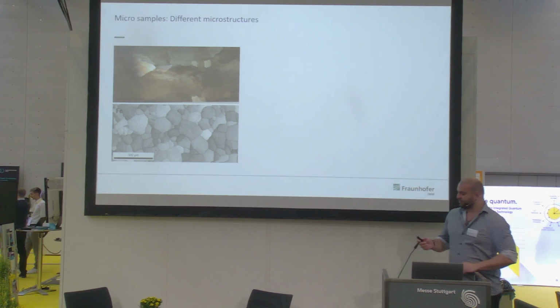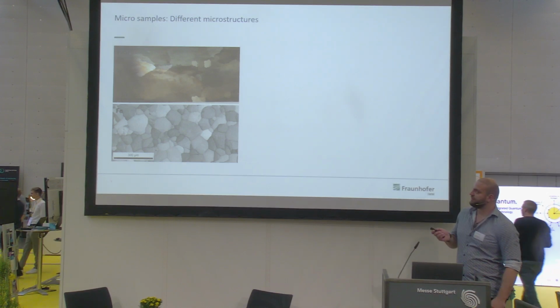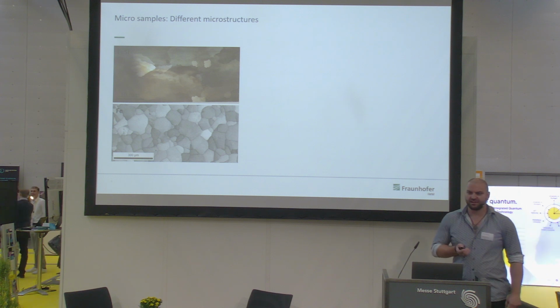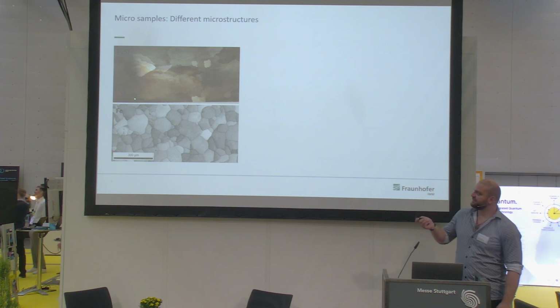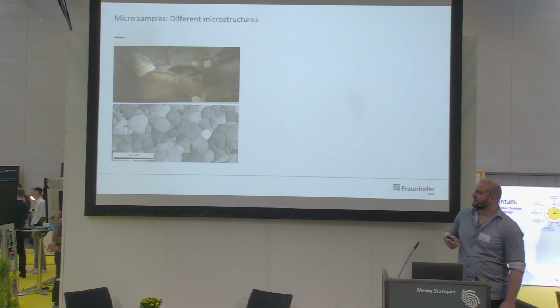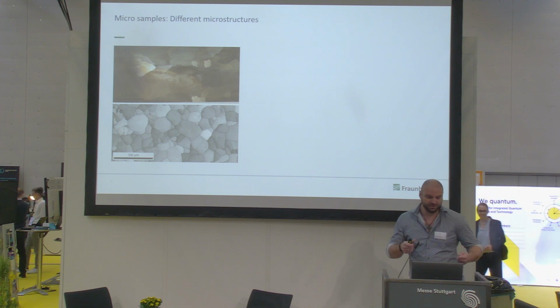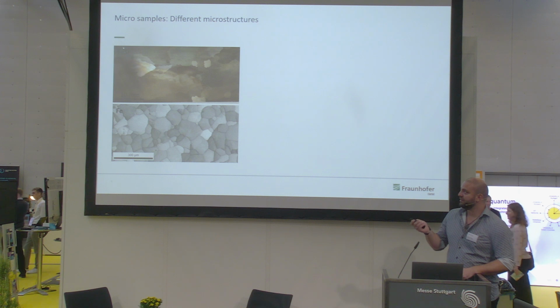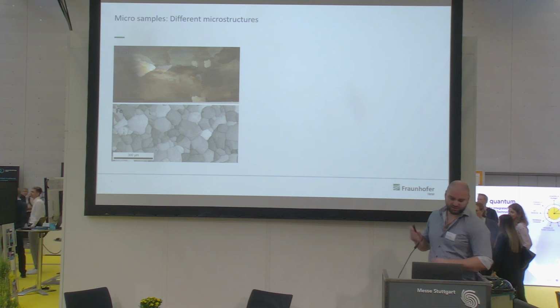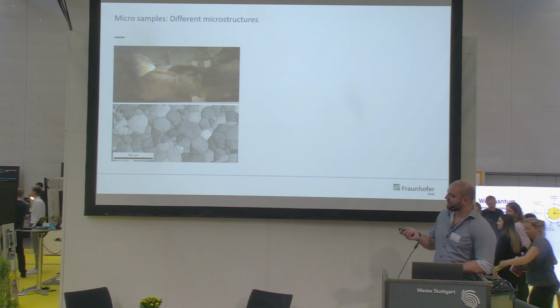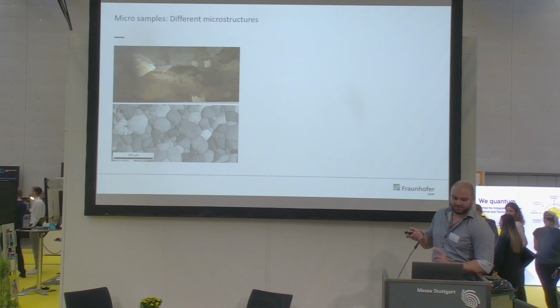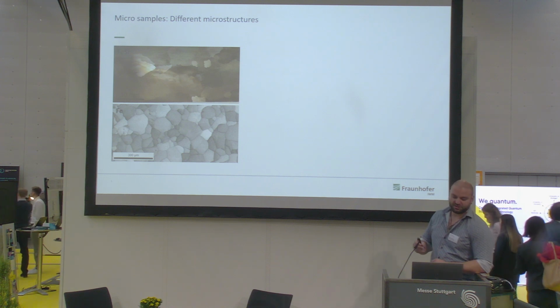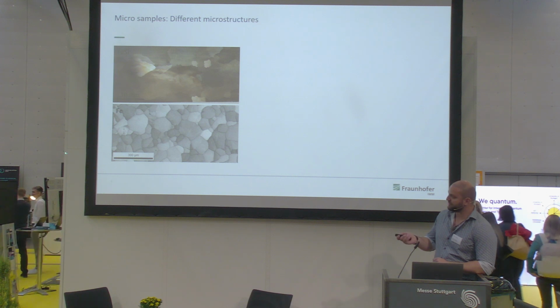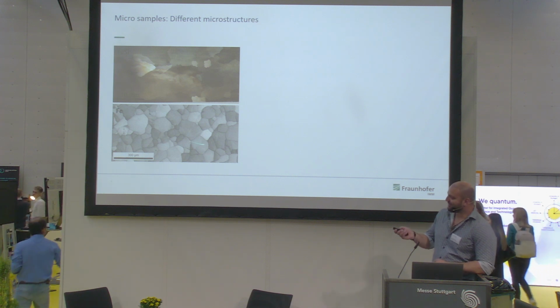Okay, in the talk here, we use two different materials. One is an iron silicon, the other one is pure iron. Why do we use exactly these two? Iron silicon, as you can see here on the scale bar, has really, really large material grains, on the order of centimeters, which allows us to cut monocrystalline samples out of a single grain of the material. Also, iron silicon is very well known for its magnetic states. It's a transformer steel, electrical steel, with very much research done on it. And pure iron has a microstructure involved, so we can have a look at what influence the microstructure in the material has on the magnetic signal. Also, you can see here the scale bar is much smaller. So we have small grains.